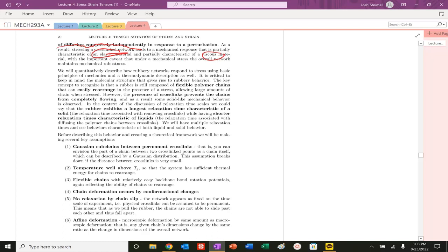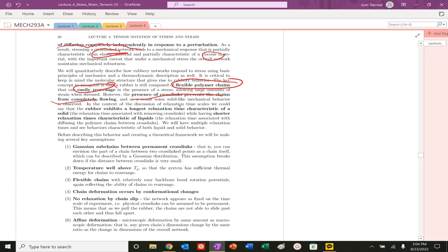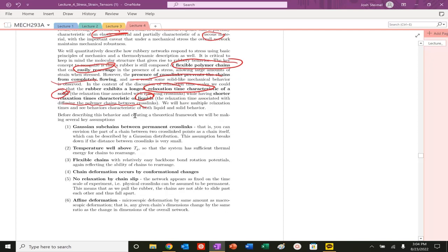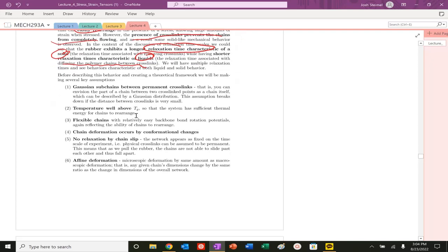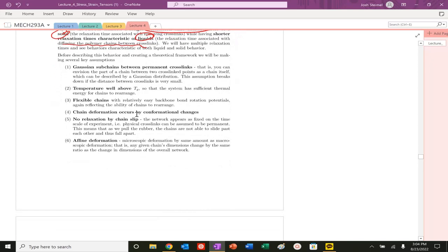It's really critical to keep in mind that the rubber is composed, as we've said over and over, of very flexible chains in between the crosslinks that can rearrange. So the presence of the crosslinks prevents the overall chains from just flowing because you have those permanent, physical, or chemical crosslinks. So we're going to have two relaxation times of a rubber, one that's going to be that solid, one that is much shorter with that liquid behavior. The liquid is associated with polymers between the crosslinks. Longer relaxation time, the solid response, is associated with eventually removing those crosslinks.